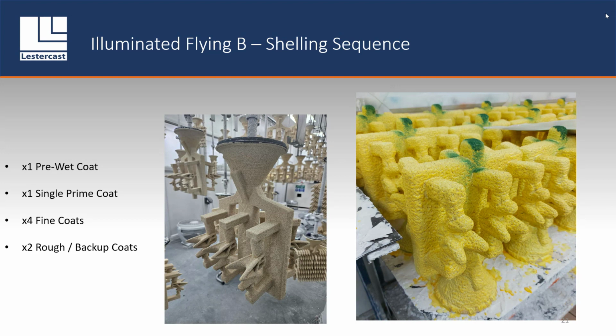This is a picture of a wax assembly that's already had, I think, its first fine coat put on. And this is a picture of the very last coat, before it goes into the autoclave to have the wax removed. This is usually around 7 to 8 millimeters thickness. Again, Martyn mentioned it in an earlier slide. So literally you've got the shape and then you offset that by 6, 7, 8 millimeters, and that gives you your thickness of shell. It's only that 6 millimeters of shell separating the liquid metal from the atmosphere. It's quite amazing.